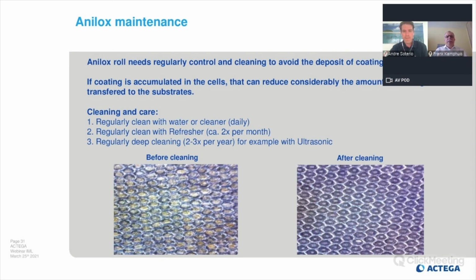What about the maintenance of an Anilox roller? That is very important. An IML water-based coating dries much faster compared to standard coatings. And that means if the coating is dried in an Anilox roller, it's difficult to clean. So you have to clean the Anilox roller daily with water or a common cleaner. And twice per month, we recommend a refresher, so a deep cleaning of the Anilox roller. And it makes sense and it's very helpful two or three times per year that you clean your Anilox roller with ultrasonic. And here you see a picture. If this Anilox roller is dirty with dried coating, then it could not apply anymore the amount of coating that is necessary. And after cleaning, you have the cells very nicely cleaned, and you can apply the right amount of coating.